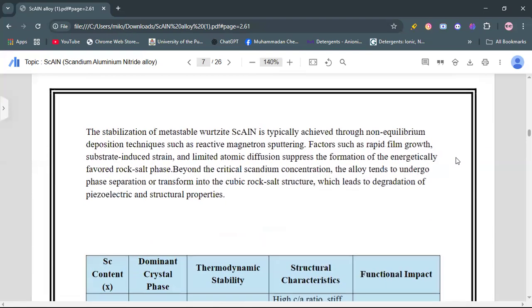The stabilization of metastable wurtzite scandium aluminum nitride is typically achieved through non-equilibrium deposition techniques such as reactive magnetron sputtering. Factors such as rapid film growth, substrate-induced strain, and limited atomic diffusion suppress the formation of the energetically favored rock salt phase. Beyond the critical scandium concentration, the alloy tends to undergo phase separation or transform into the cubic rock salt structure, which leads to the degradation of the piezoelectric and structural properties.